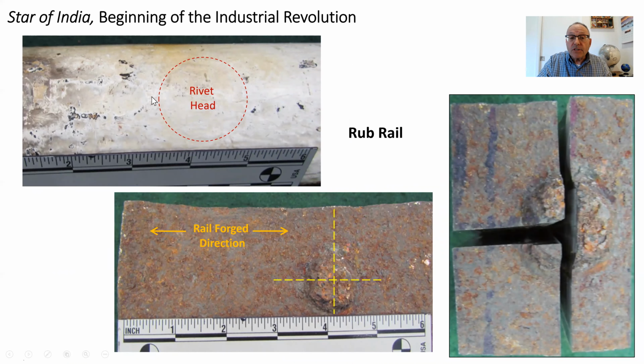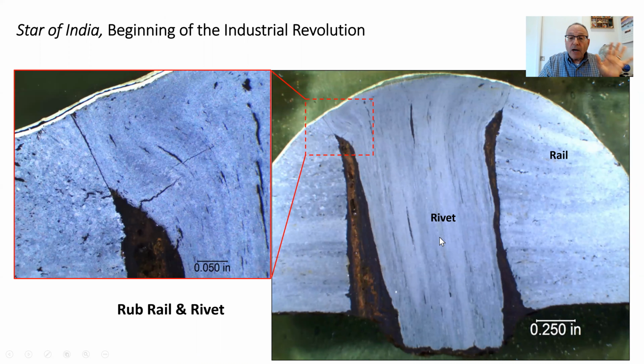This is the outside of the rivet of the rail, so it's not extremely apparent, but if you flip it over, here's the bottom of the rivet coming through. And so what I did is I cut this through the section here, and then I cut this through this way so that I could look at the microstructure of the section through both the rub rail and the rivet. And so what I did is I mounted it, we polished it, and we etched it so that we could see some of the constituents or the product that made up this material.